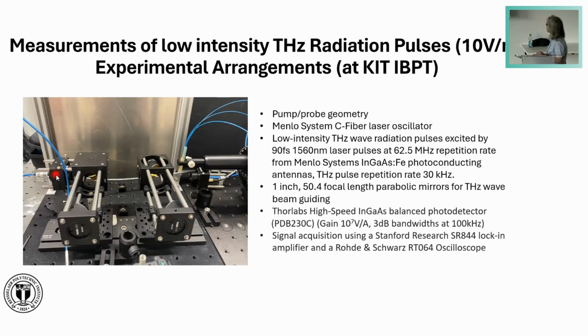The terahertz radiation source is a Menlo Systems photoconducting emitter. We use an arrangement of 4 parabolic mirrors to focus the radiation on the sensor, which is here in its sample holder, on an XYZ and rotary stage. For signal acquisition, we use basically the same setup as at Oak Ridge, only that we use a lock-in amplifier. For the lock-in amplifier, the terahertz pulse repetition rate is modulated at 30 kilohertz. And the balanced photodetector is identical to the one which was used at Oak Ridge.